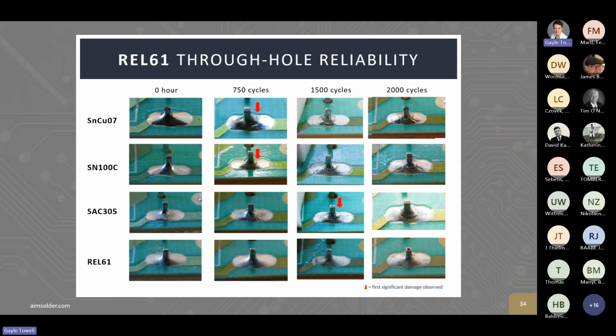Here we see some of these joints at 0 hour. Everything looks fine across all of the alloys. After 750 cycles, we're starting to see some failures in that tin copper alloy and an SN100C. At 1500 cycles, SAC305 has failed. 2000 cycles, we still have REL61 going strong.